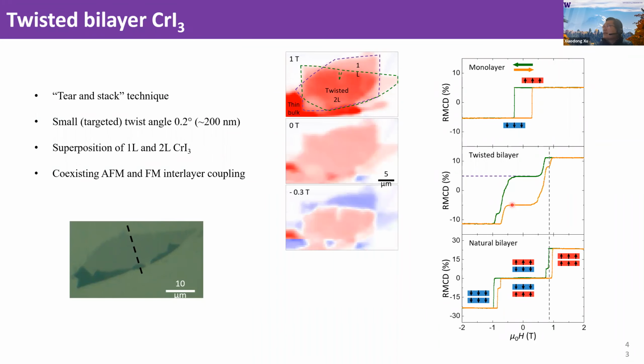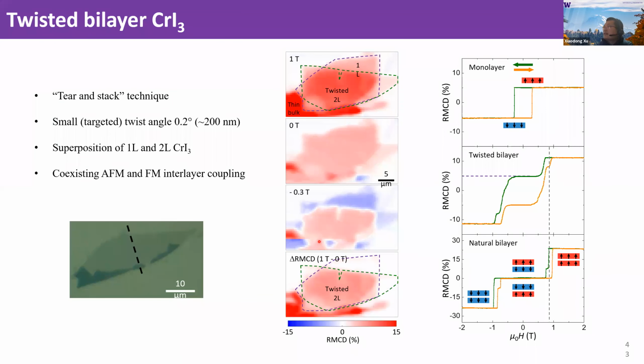We can perform these MCD mappings at different magnetic fields. In the middle I show 0 Tesla, and at the bottom I show minus 0.3 Tesla. Minus 0.3 Tesla is already larger than the spin flip field of a monolayer, but smaller than the bilayer. So you can see that for the monolayer the color already changed because the magnetization flipped direction. But in the middle, the twisted bilayer hasn't changed. If I take the difference between the 1 Tesla and 0 Tesla maps, we come up with this map, where the middle is identified as the twisted bilayer.